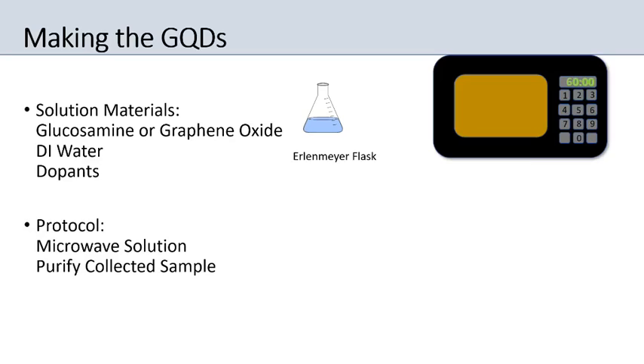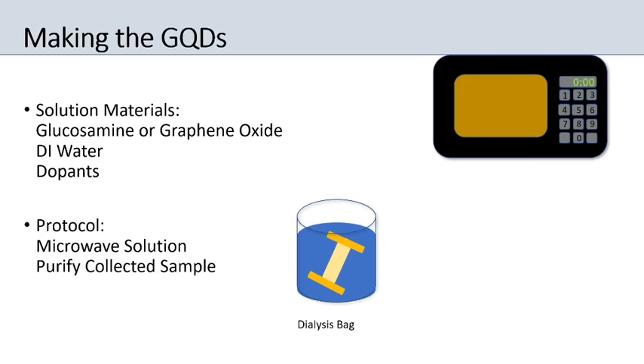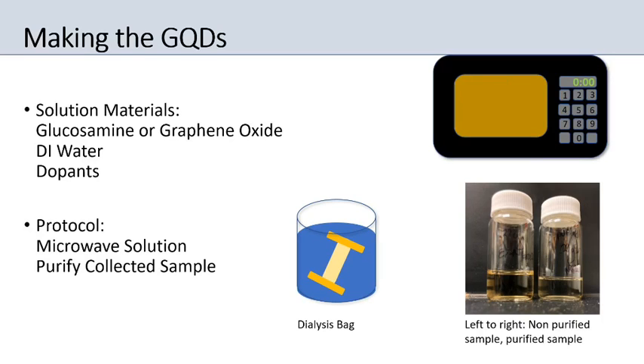We dissolve that into water and add whatever our various dopants are, and then we microwave it for about an hour. After it gets microwaved, we purify the sample with a dialysis bag. And what's happening in the purification process is any glucosamine or any graphene oxide that did not become a graphene quantum dot is getting filtered out of the sample. And so you can see a clear difference here in the color. A much darker sample was not purified, and then after purification, it's a much lighter sample.